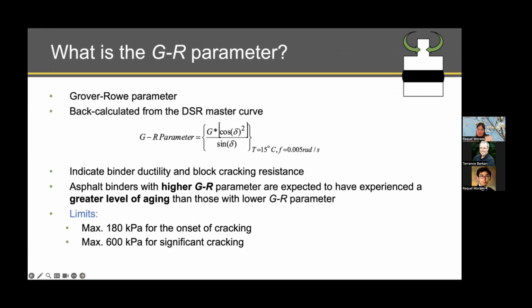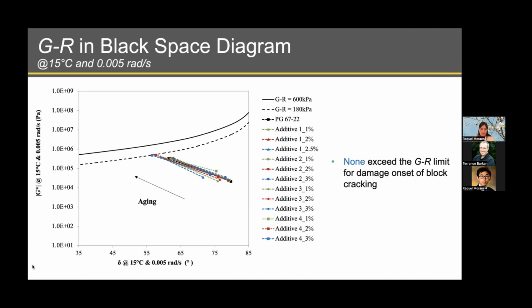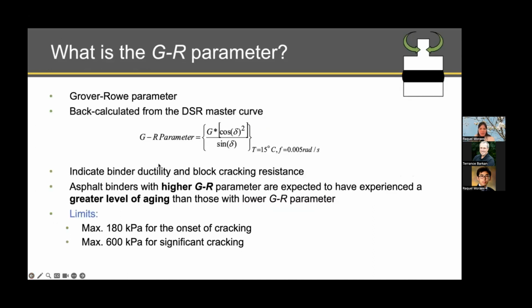And lastly, the last parameter that we used to evaluate was the Glover-Rowe parameter, that is this GR here. This parameter is obtained from dynamic shear rheometer master curves, where the binder is tested at several temperatures and several frequencies. And we use this specific parameter to see the ductility and block cracking resistance of the binders. What has been seen and has been proved by field data is that when the binder starts to get aged or more oxidized, we see an increase on the Glover-Rowe parameter. Therefore, an increase on the cracking susceptibility of the binders.